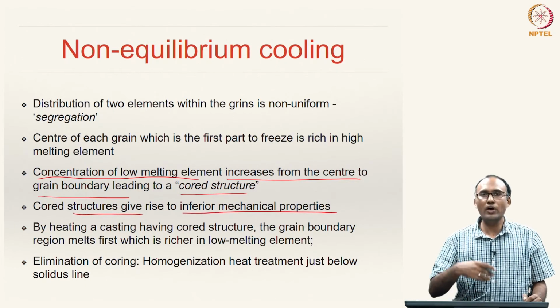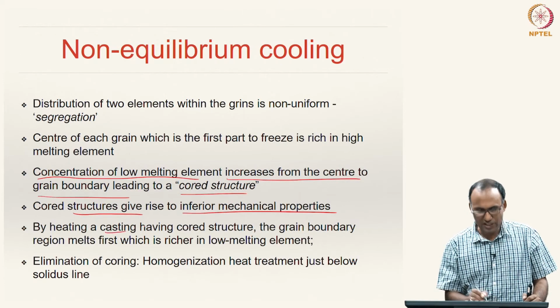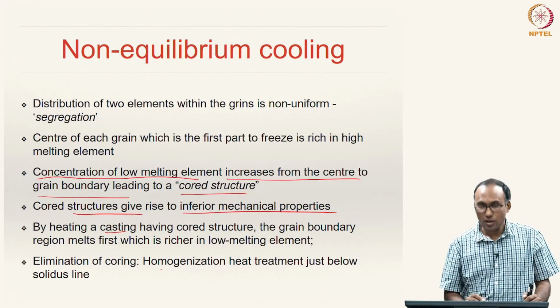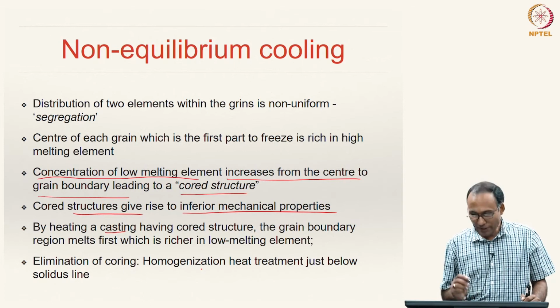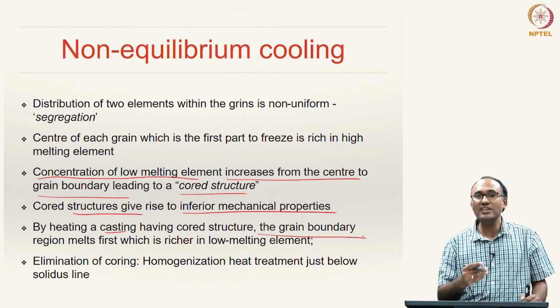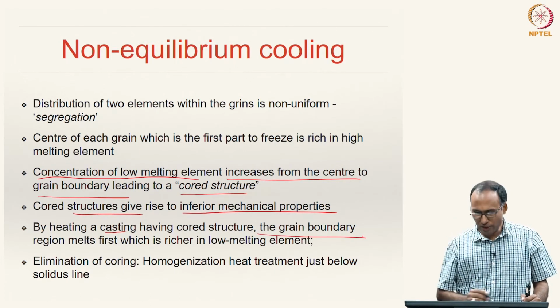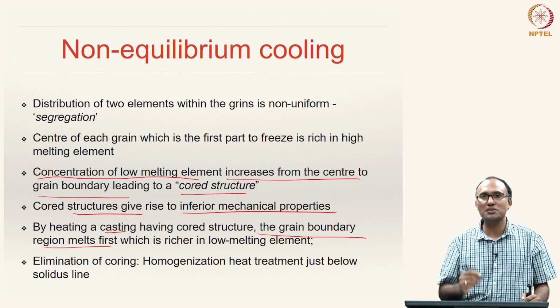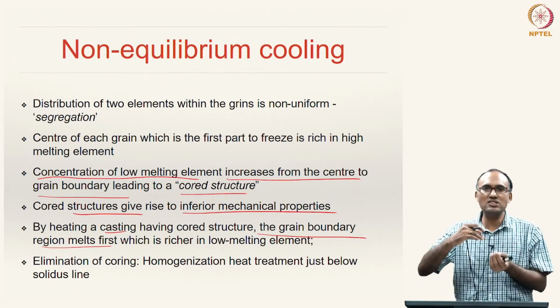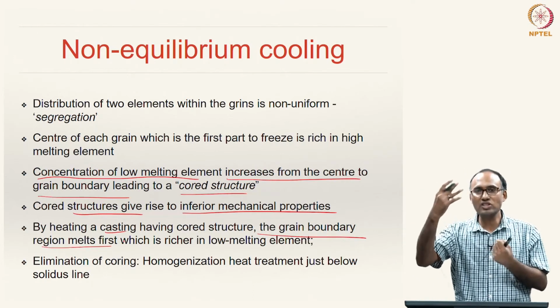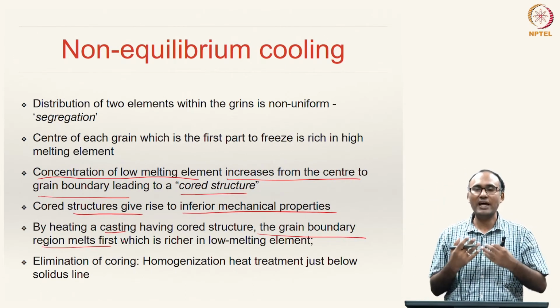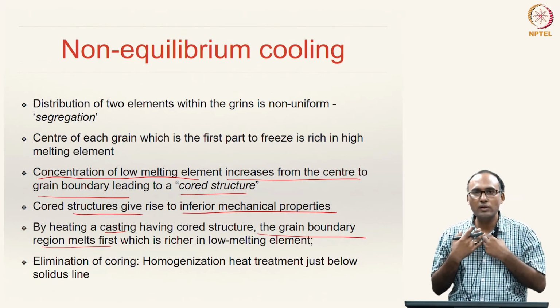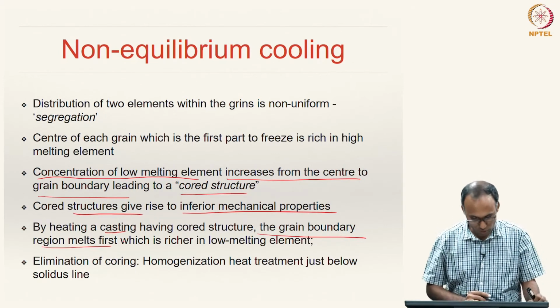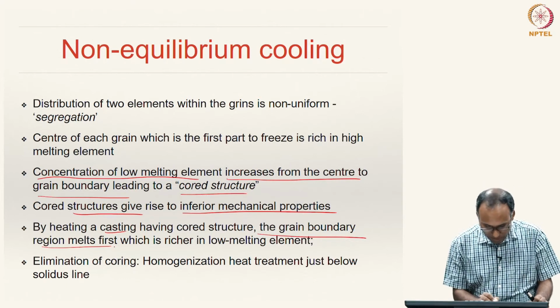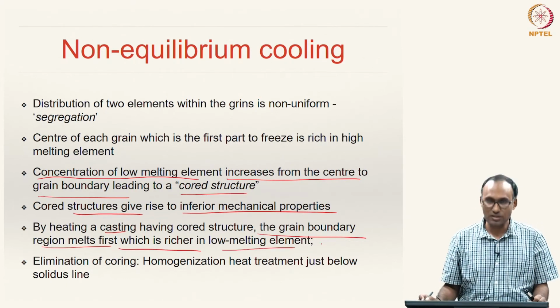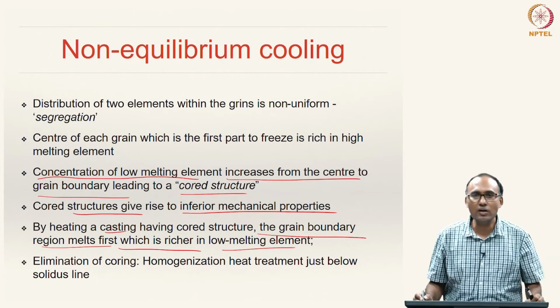Why? Because if you are heating a casting made out of such a system, such a cored structure, what might happen is the grain boundaries, because they are rich in low melting alloy, the grain boundary might actually melt first. So, if you imagine using this component at high temperatures, the grain boundaries will melt. As a result, the material might actually give in, that means it might actually fail. So, the grain boundary region melts first, which is richer in low melting element, and that can be detrimental for